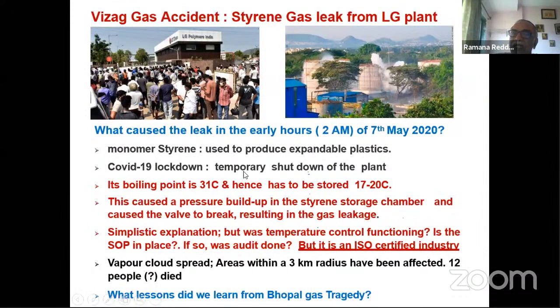So it was advised that styrene should be, this is the ISO condition, stored at 17 to 20 degrees centigrade. And if you see the MSDS sheet, they also write this 20 degrees. This caused a pressure buildup because this failed, according to the simplistic report. So many days they did not maintain it, or it failed, whatever it is, because maintenance of the cooling system might not have been done. That led to the pressure buildup, to the breakage of the wall, resulting in the gas leak.